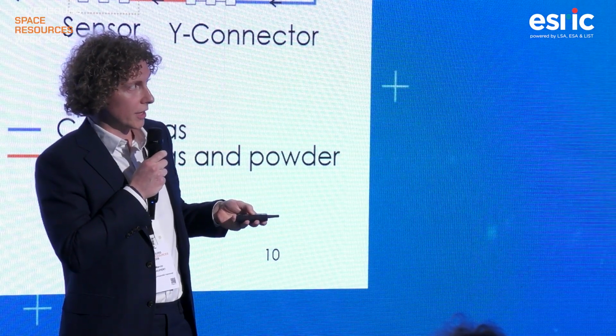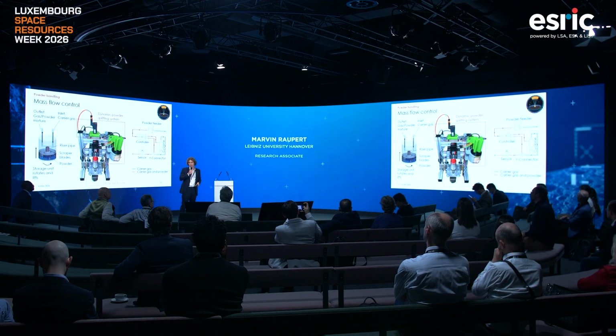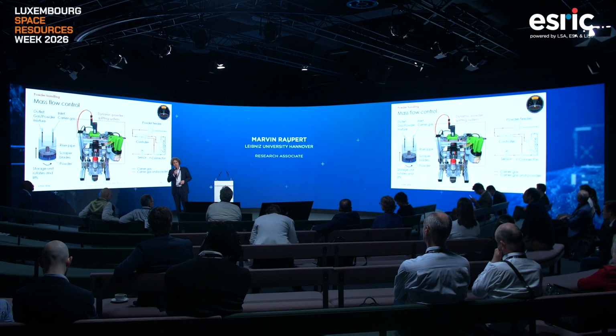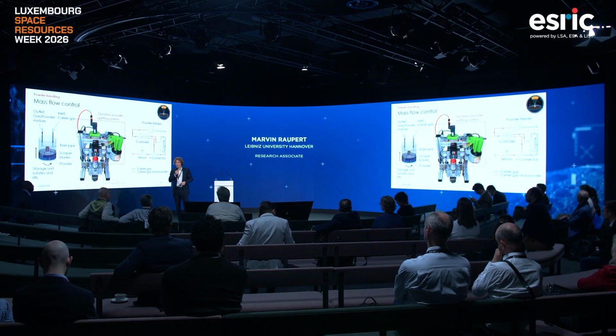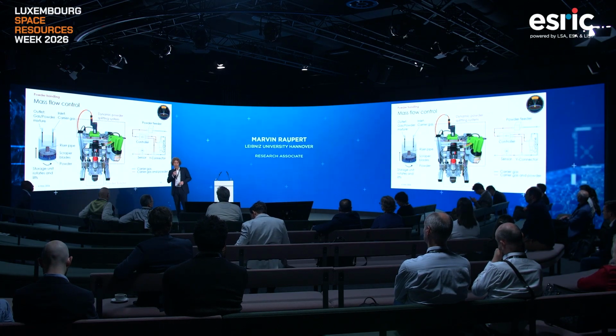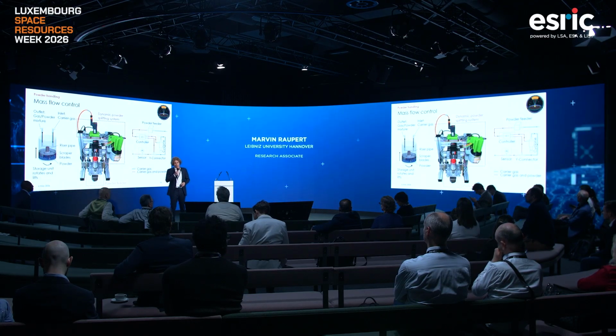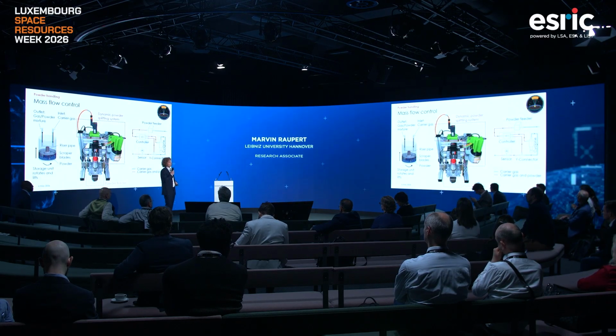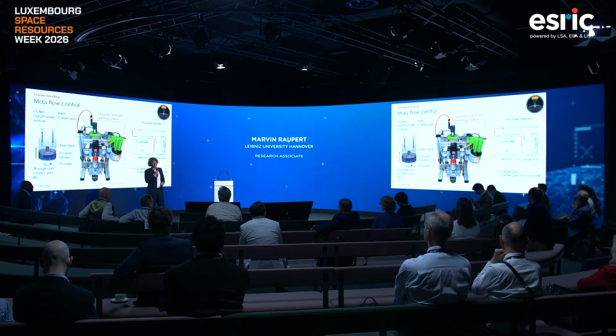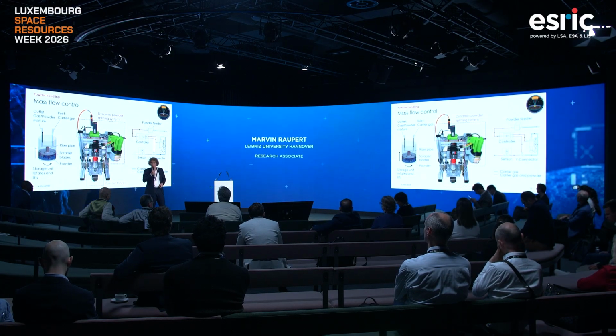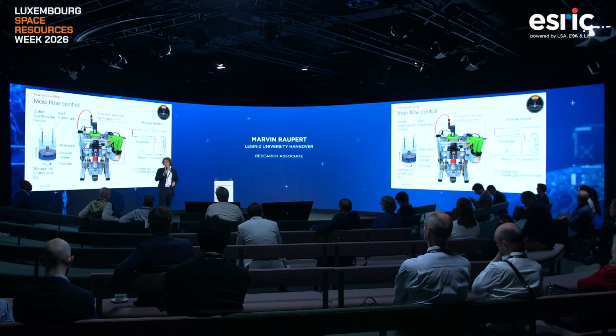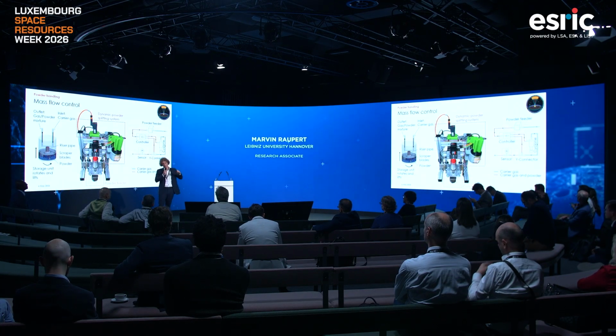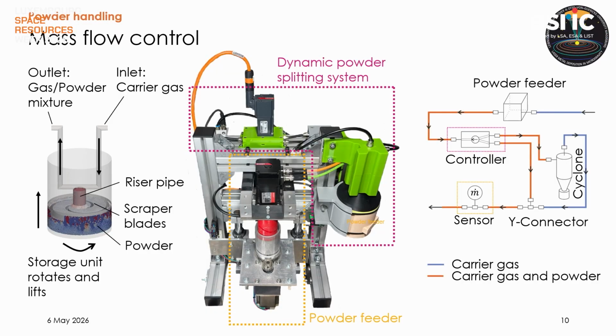So the powder is in the powder container. The powder could rotate and move up, and then with the help of a scraper blade, the powder will be scraped into the center, goes then into the riser pipe, and one tube, the inlet filled with argon, the carrier gas, catches up the particles, and then we have a flow of a particle gas mixture. In the beginning, we thought that with the rotary speed and the movement in the upper direction, we could control our mass flow, but that didn't work.